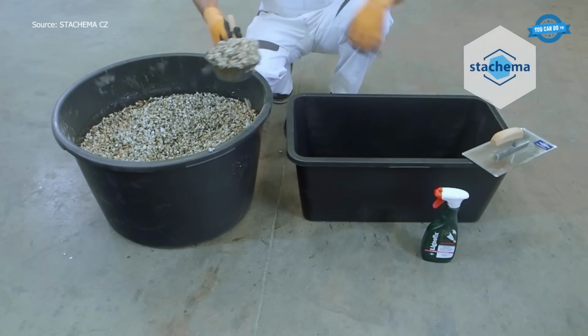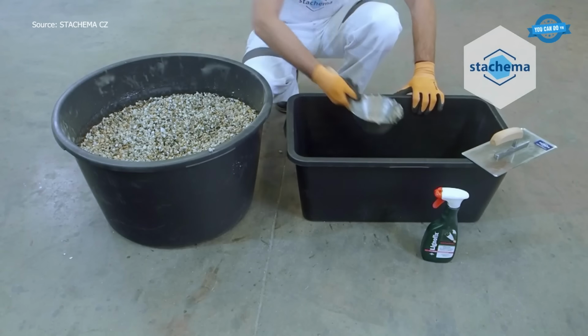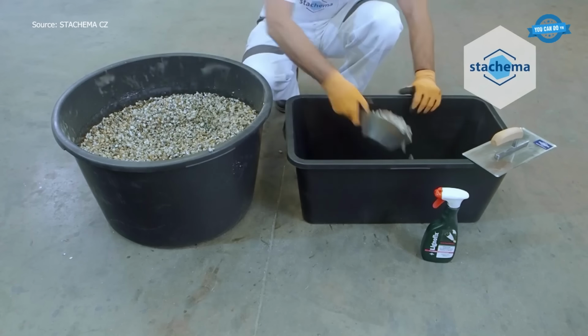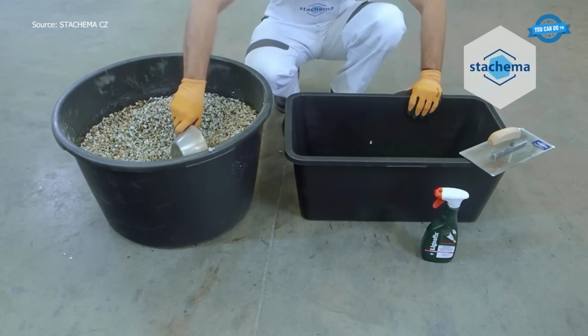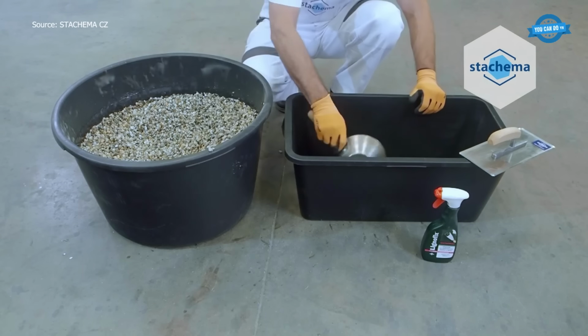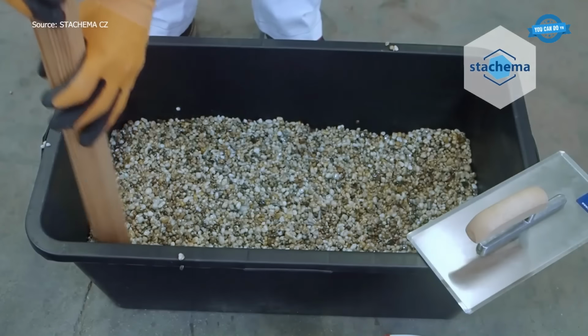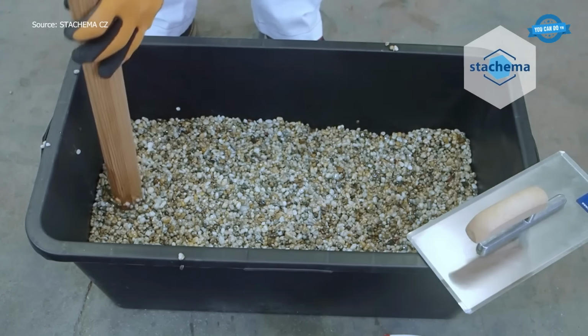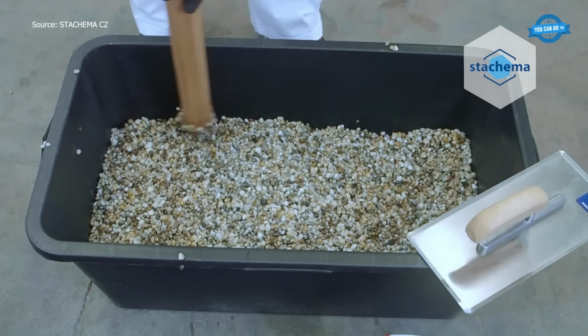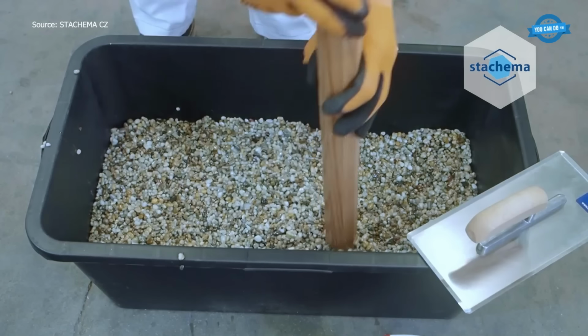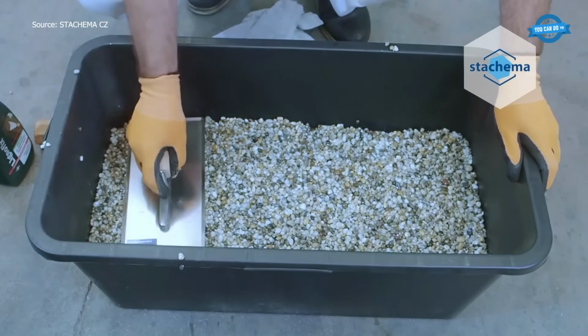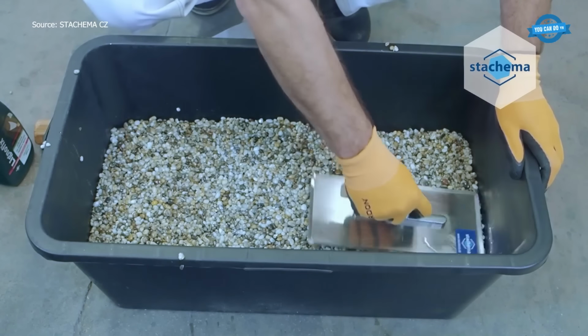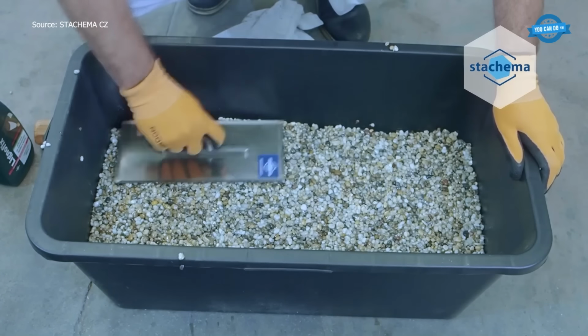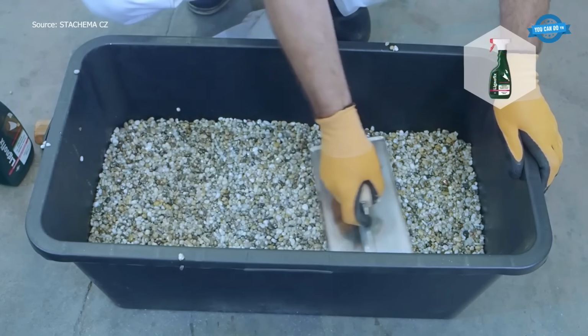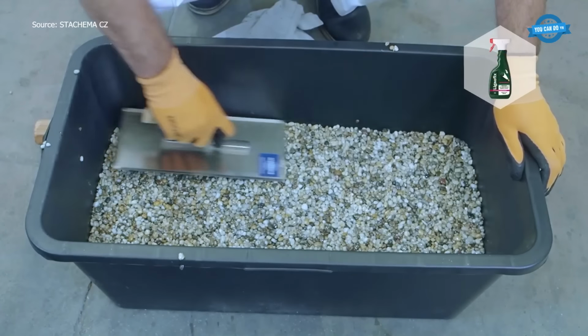Binder is then introduced, following the defined ratio of 10 kilograms of epoxy to 160 kilograms of aggregate, ensuring proper coating without excess resin. Mixing continues until the surface of each stone is evenly covered, not flooded. This is the moment where mistakes quietly multiply if attention slips.